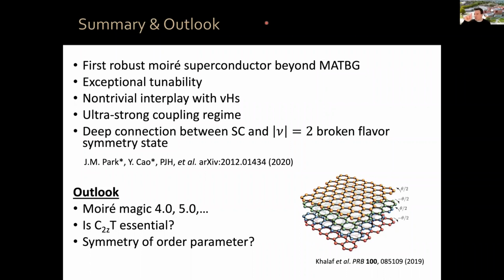I should mention one thing, perhaps, which is that the system is a little bit different from bilayer graphene in that we have the massless Dirac band too, right? So as we add charge density to our system, initially, the vast majority of the charge density goes into the bilayer flat bands, right? But then as you keep adding charge density, you start putting more and more density into the massless Dirac band. The density of states of the massless Dirac band increases. So it gets harder and harder to reach higher filling factors of the flat bands.